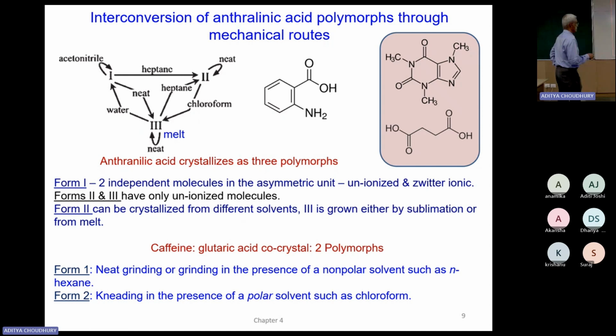So you can use this solvent while grinding, you can convert from one to another. In one case, if you add water, it goes from form 3 to form 1, and in chloroform 2 to 3, and so on and so forth. This is clearly mentioned here. Then the question, how do they do it? By using powder, because they have the crystal structure already. Okay, they crystallize it and they determine the crystal structure. But using the powder pattern, they can very easily do it.